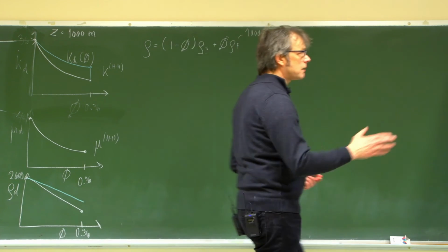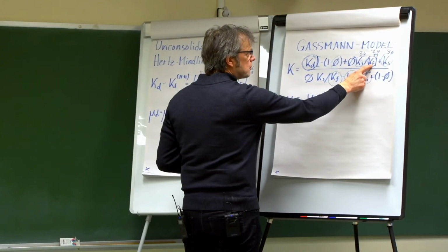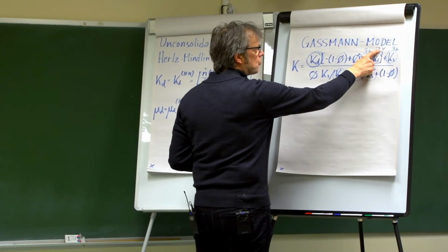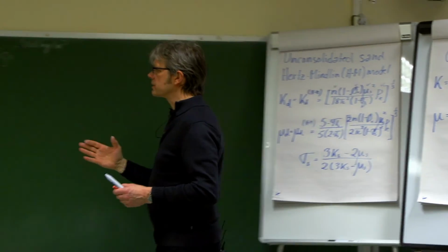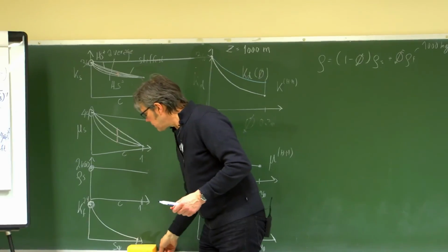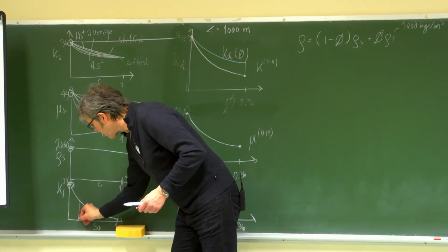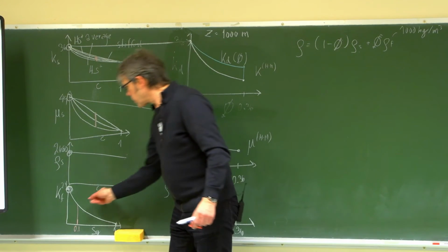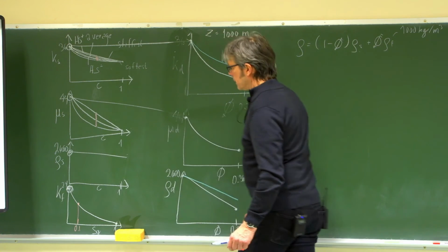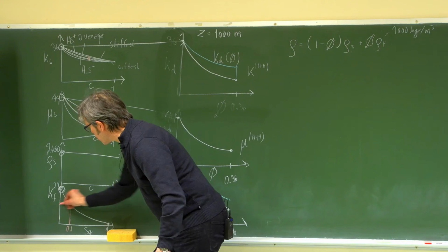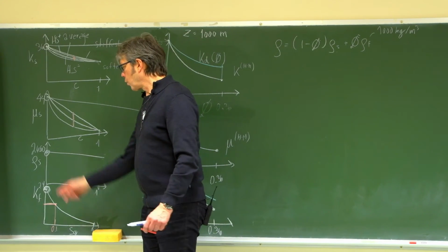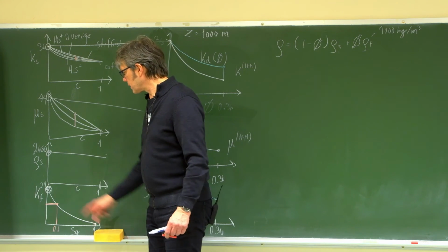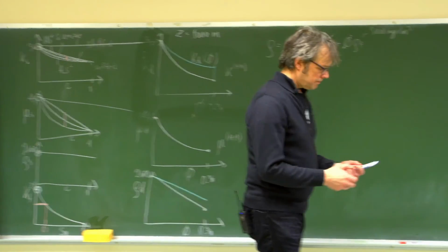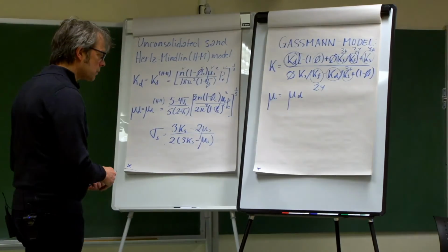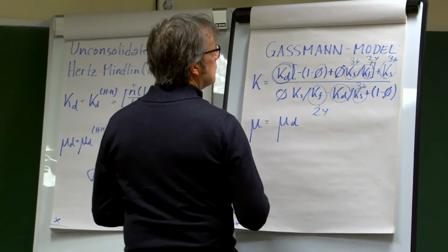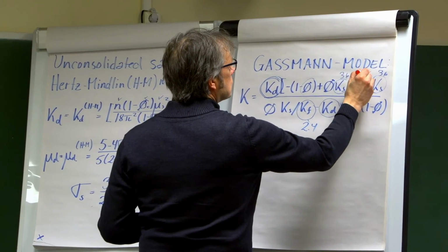Okay, what does that mean? I add 10% of gas, that means that the bulk modulus here of the fluid would change. I can't use 2.4 anymore because that's for water. But I have my relation over here. So let's say I add some 10% here of gas. And then you see that the Kf is jumping quite a lot. Maybe 1.9 or 1.5 or something. It's almost half here. So if I add this new number here, I could use a red. Just say then, okay, then this becomes 1.5.